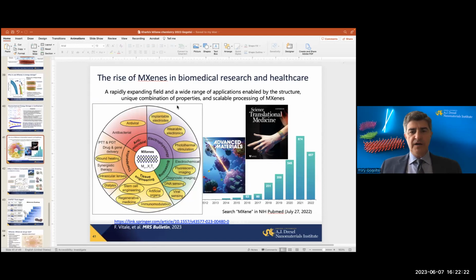This work was done in collaboration with a colleague initially from Qatar, and it started not with the medical application. It started with the goal to prevent fouling of membranes for water desalination, to minimize growth of bacterial films. And then it was shown that pure MXene has antibacterial properties. The exact mechanism of the action is still being discussed. What is interesting is that it shows antiviral and antibacterial properties, but it depends on the type of bacteria. It has much better antiviral properties compared to larger bacteria. And again, there are still arguments about the mechanism.